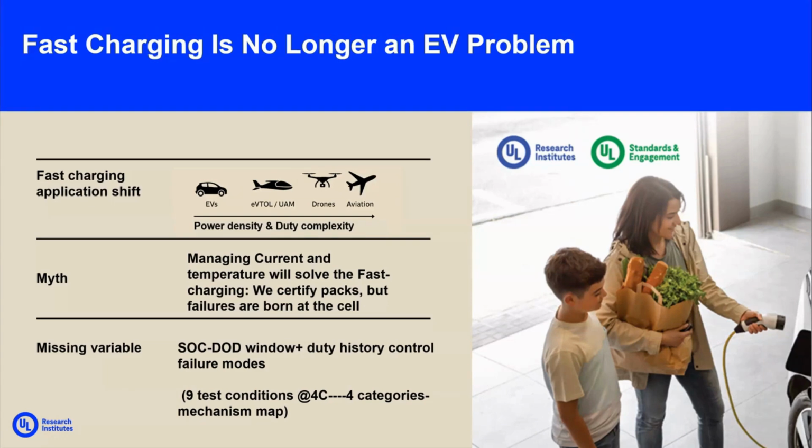As I mentioned, for this one we considered the design of experiments based on the operating SOC and DOD windows. Fast charging is generally considered as charging the battery fully within 15 minutes. Based on that consideration, we considered the 4C charge rate for the cells. The test protocols use the same charging and discharging current rates, and we have not provided any constant voltage charging mode in our system.